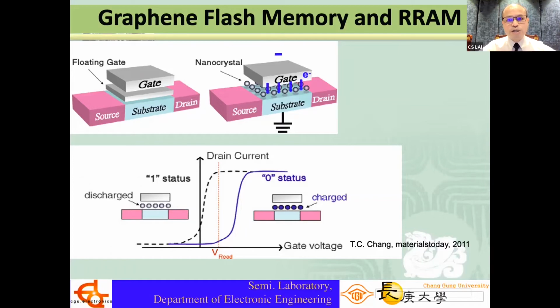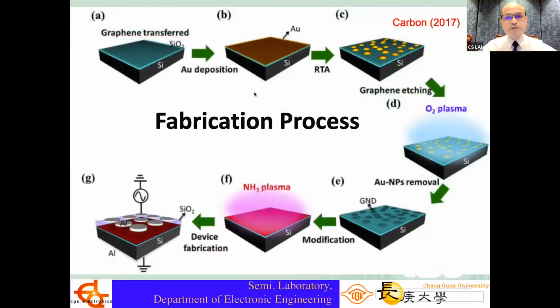Here we use graphene as the floating gate. How do we prepare it? Eventually we have the structure like in figure G. The top gate is a metal gate, with an embedded floating graphene nanocrystal structure. We transfer the graphene first, and then deposit gold. After high temperature rapid thermal annealing, the gold nucleates and forms nanodiscs. The nanodiscs serve as a hard mask to pattern the graphene into nanodiscs. So we can prepare GND, graphene nanodisc structures, as our nanocrystal floating gate.